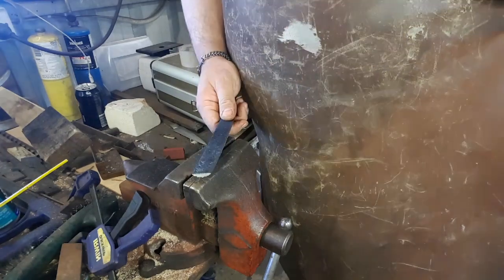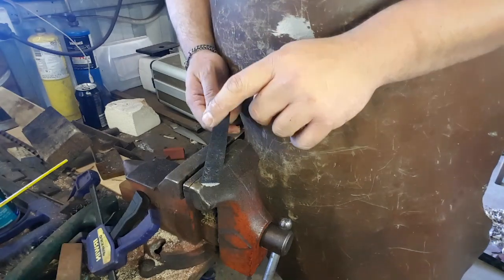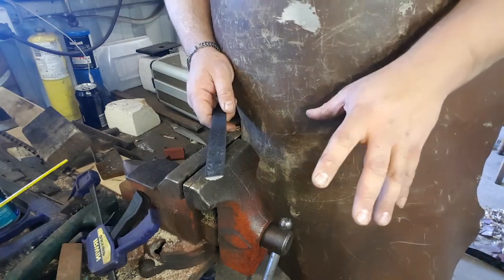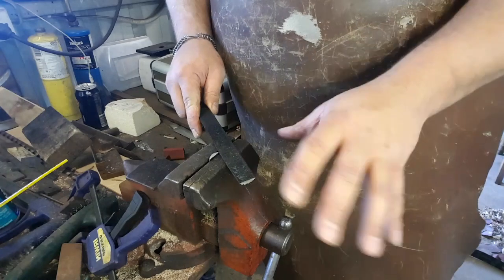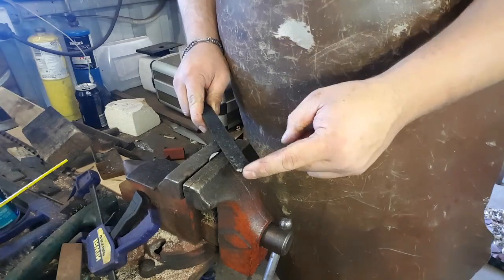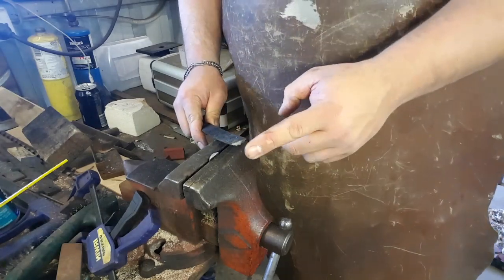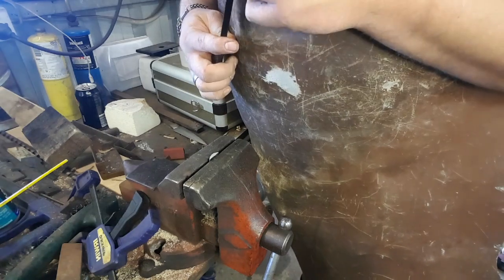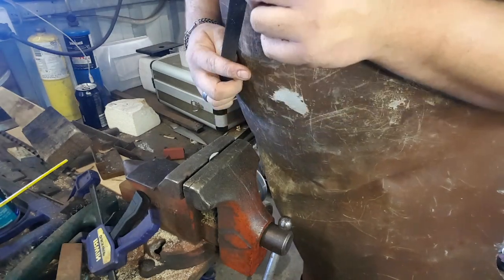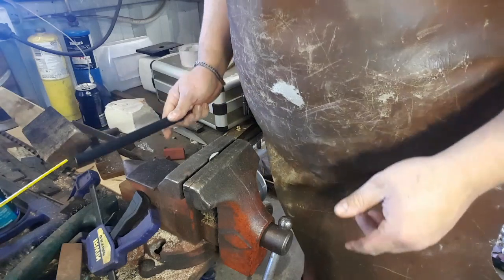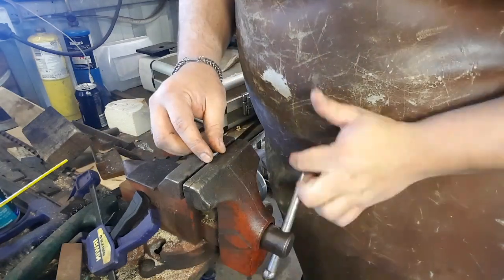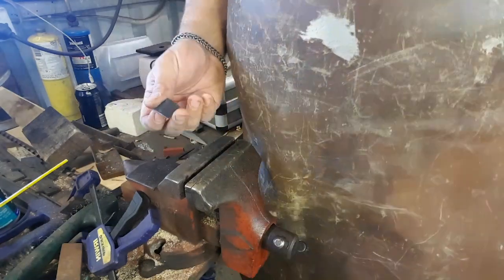And I suggest, if you're just getting into bladesmithing, do some test pieces. Don't even make a blade out of them. Just forge a piece into something, heat treat it, and then check for your grain structure. Get your grain structure dialed in. But I can tell that I did a really good job on that. That is solid heat treat or solid hardening. But as you can tell, that is really too brittle.